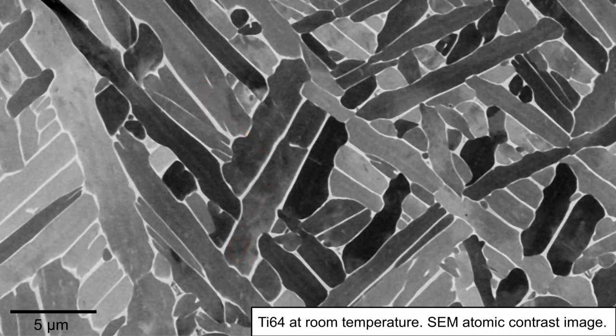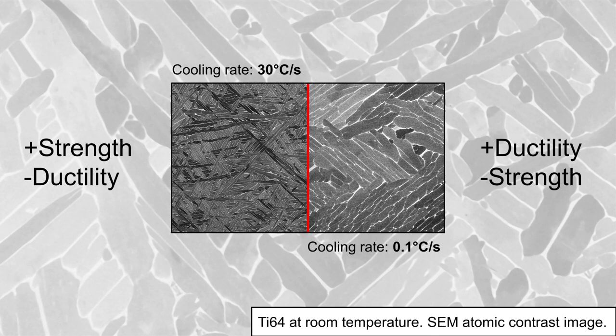It is from this fine microstructural scale that Ti6-4 gains its superior strength, which also contributes to its other excellent mechanical properties. Furthermore, the mechanical property balance can be customized by controlling the cooling rate during solidification or, as is more often the case, the subsequent thermomechanical processing. For example, a fast cooling rate can produce a very fine microstructure that results in high strength and reduced ductility.